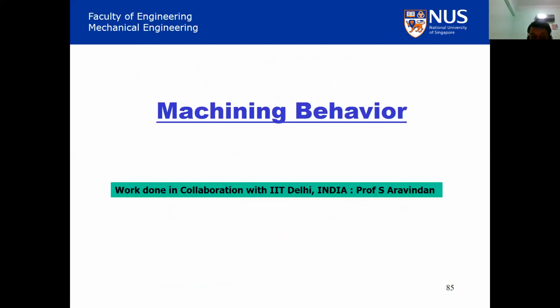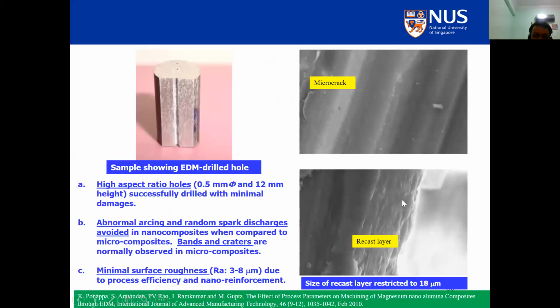Machining is also a very important facet if you want to take the material to the industry, because most of the components are machined. And this work we did, the initial work was done with IIT Delhi, Professor Aravindan, and they wanted to study the machining aspect for deep aspect ratio holes. Their results showed that we can drill it, no abnormal arcing, and the surface roughness is acceptable. Some of the pictures that they shared to verify their observation.